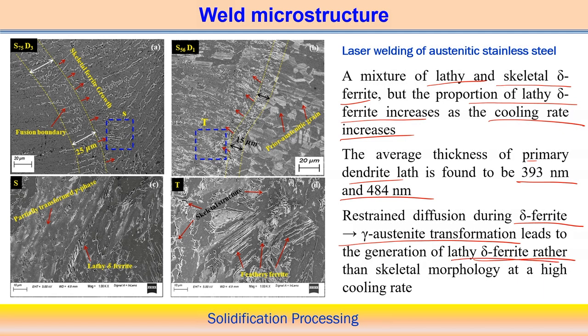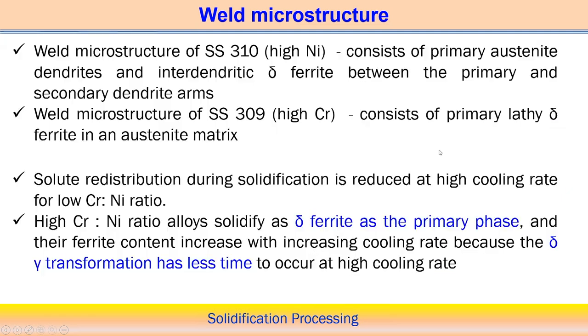Lathy delta ferrite is promoted rather than the skeletal morphology at very high cooling rate. Here also you can see the cooling rate is very high. We can expect the lathy delta ferrite structure in the austenitic case, as compared to the skeletal morphology, to be more promoted. So I mean to say that the structure is very complex, a mixture of different kinds of morphology and grains, and the structures are completely different at different cooling rates. But to some extent it is more or less material specific, and here we try to understand this type of structure associated with austenitic stainless steel.